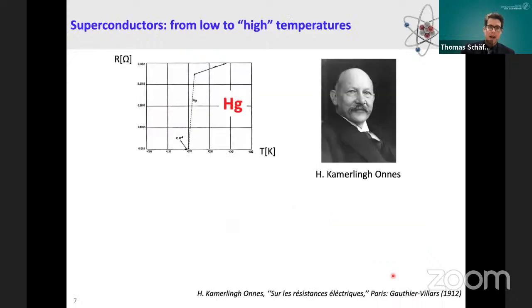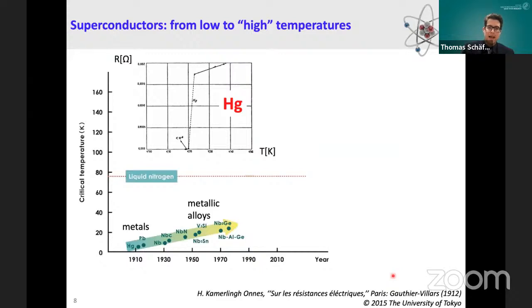Let us first start with superconductors. As you probably all know, superconductivity was discovered in 1911 by Heike Kamerlingh-Onnes, who cooled down mercury with liquid helium down to more or less 4 Kelvin. And he observed that the resistivity first was dropping quite smoothly as he cooled down, but then it had an abrupt drop to more or less zero resistivity, which he could measure. This phenomenon is now called superconductivity. After this initial experiment, there were initiatives to combine metals into metallic alloys to raise the temperature where this drop of the resistivity happens, which is called the critical temperature.